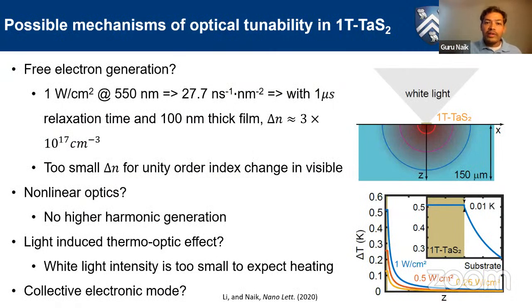And then we wanted to find out, for this white light case, what are the possible mechanisms for optical tunability? Is it free electron generation? That is simply ruled out because we have such low intensity of illumination that you cannot generate so many electrons to change optical constants by unity order. And what about nonlinear optics? We did try looking at some higher harmonic generation. We didn't see any such possibility. Again, our intensities are very low. And what about a light-induced thermo-optic effect? Just light causes heating, and heating changes refractive index. That is probably the most serious contender here.